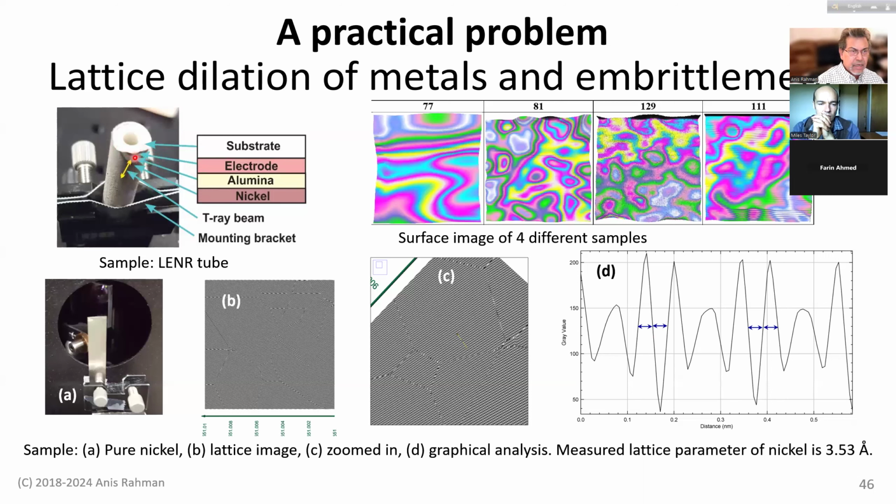This rod was polished at an oblique angle so that the layers are exposed. And these are the layers that we then focus the beam on. As you can see, it's at an angle, not purely vertical. The reason it's mounted at an angle is so that the beam is vertically incident on those layers.